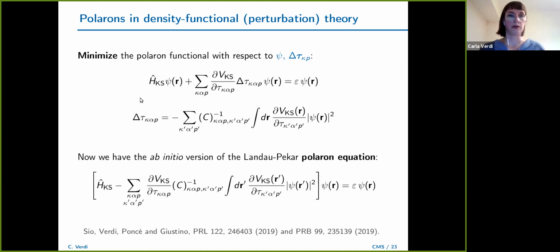And if we plug this delta tau inside the first equation, we have this expression here that looks awful, but believe me, it's not that awful. And it basically is the ab initio version of the Landau-Pekar polaron equation. This time we have much more physics in it though, because this time we are treating the lattice not as a continuum. We have an actual band structure. And we are taking into account all possible electron-phonon interaction. So you see the Kohn-Sham Hamiltonian plays the role of the kinetic term, the one-body term with the effective mass that was in the Pekar equation. And then this uglier term is the electrostatic part.